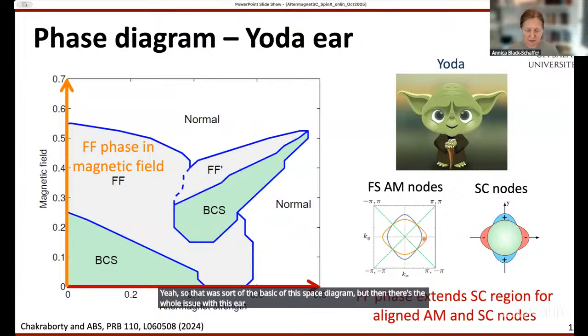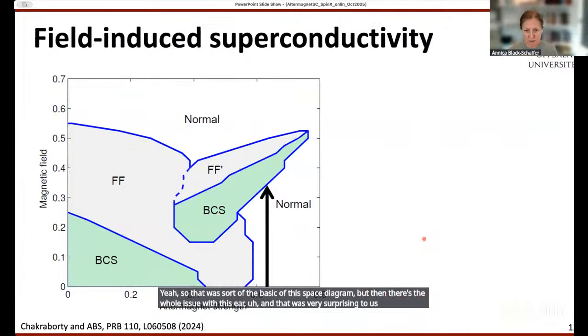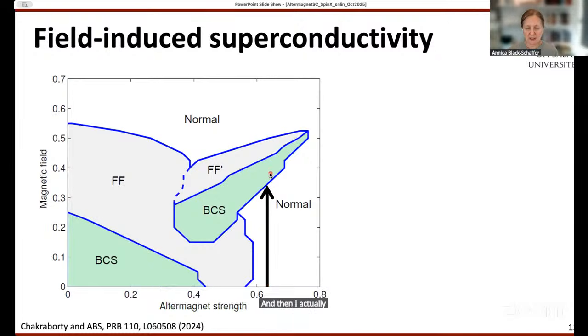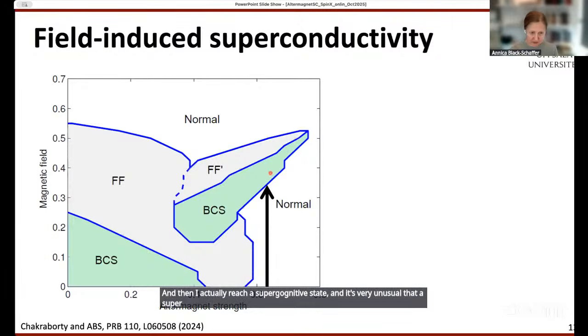But then there's the whole issue with this ear. And that was very surprising to us. Why do I get that? Because in particular, I can go along a path here. So I have an altermagnet here, and then I turn on the magnetic field, and I start with something that's not superconducting, and then I actually reach a superconducting state. It's very unusual that a superconductor appears when you turn on a magnetic field. It's usually the other way around.